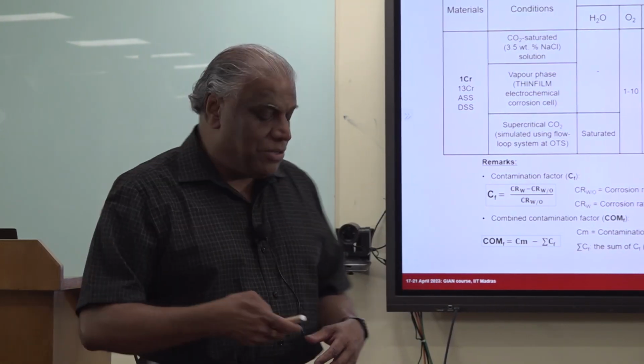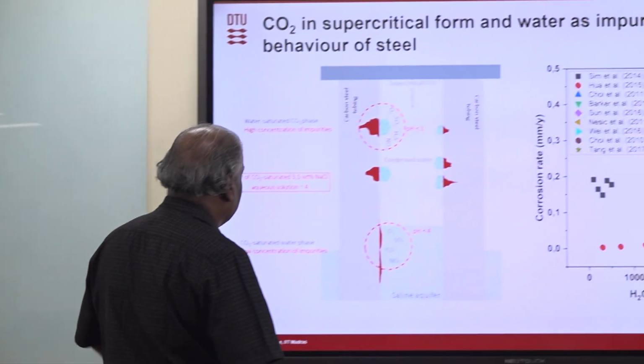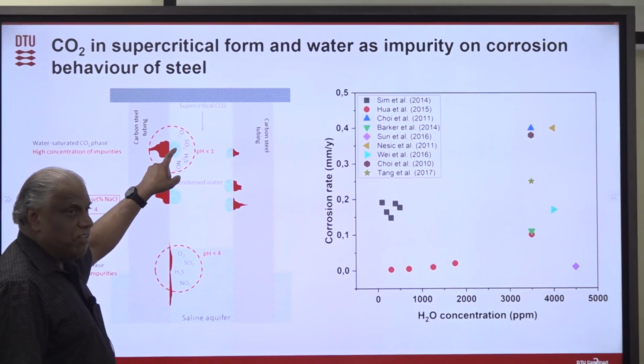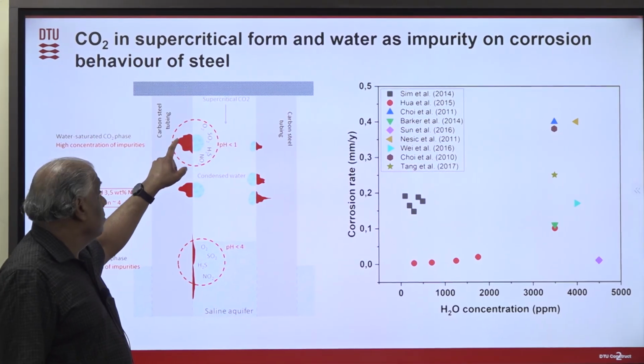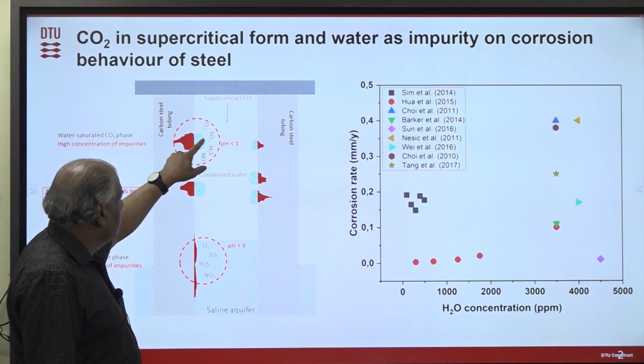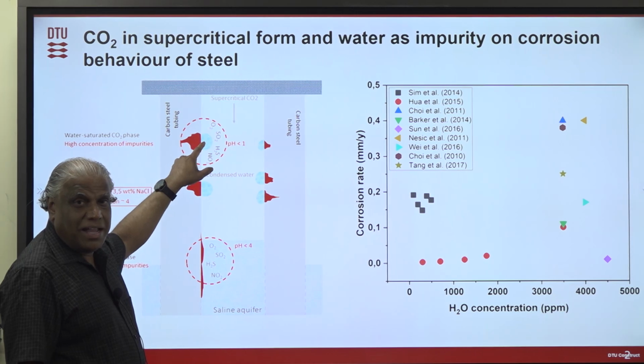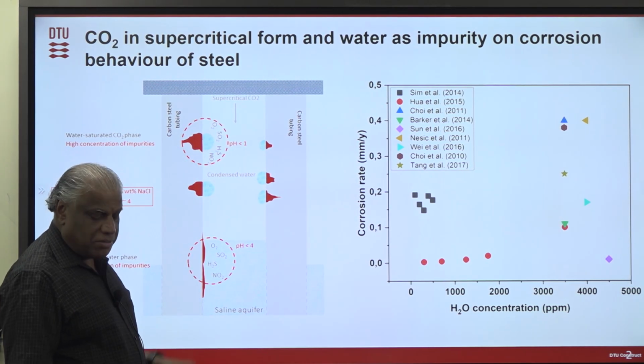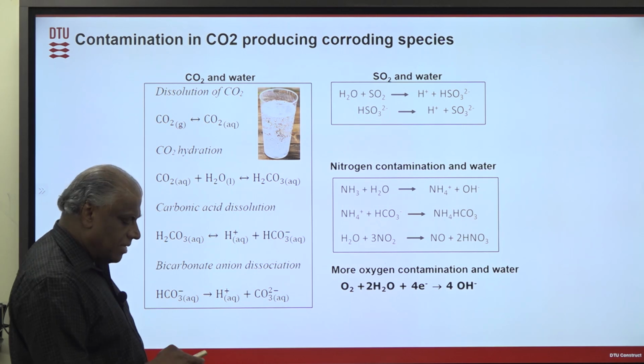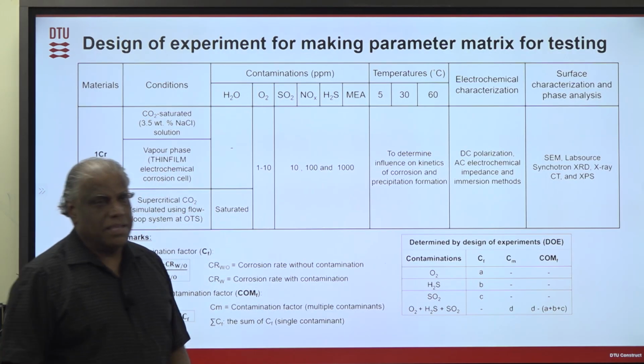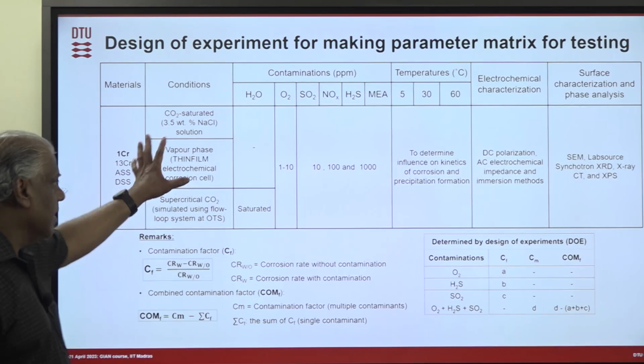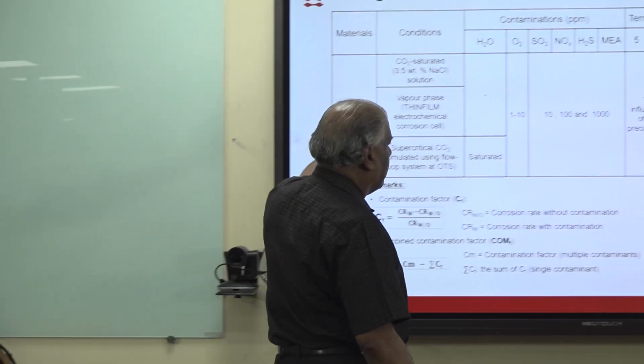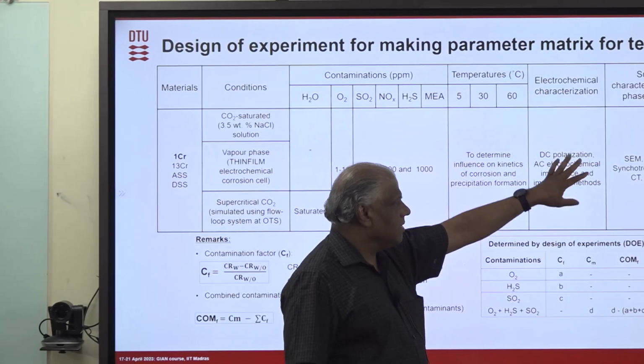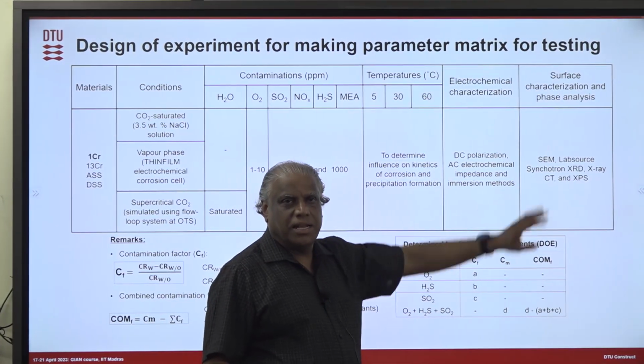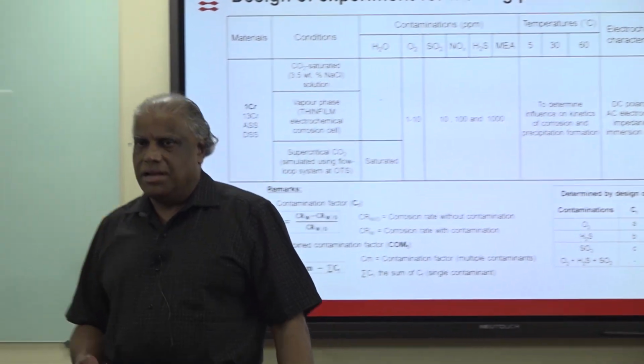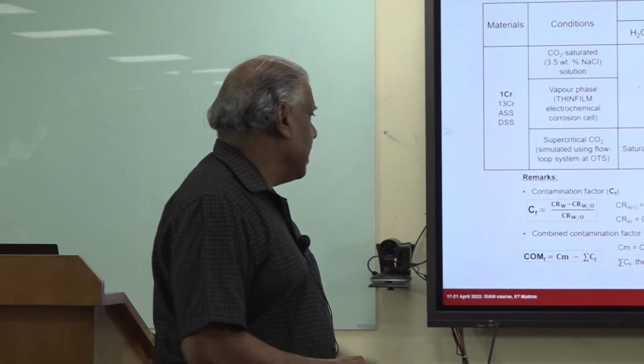At the same time, when we do that, we want to simulate this condition here. Although there is 50 ppm SO2, when it is dissolved in water, you will have a very high concentration. That high concentration we are simulating, and that's the reason that we go up to 1000 ppm in the testing. So then we do these different contaminations and we mix them, and then we do the DC polarization, AC impedance, and subsequent analysis with SEM and things like that to understand how the corrosion is occurring. So that's to learn the mechanisms.